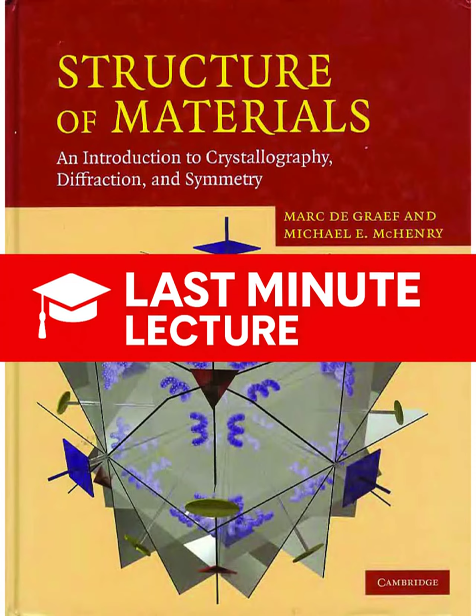It really does. Next, we look at a pyroxene mineral, jadeite, NaAlSi2O6. This is the highly prized ornamental gem jade. It also uses these infinite SiO4 tetrahedral chains. But unlike wollastonite, which uses large calcium polyhedra, jadeite chains are linked through aluminum octahedral coordination polyhedra. And that gives it a very particular look.